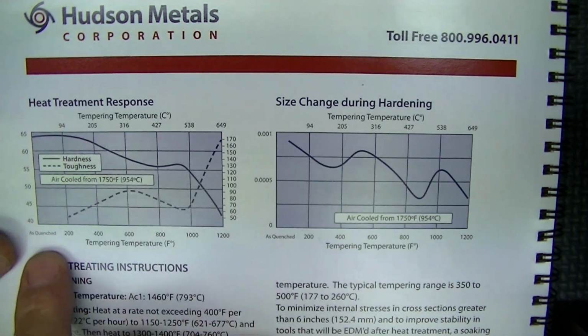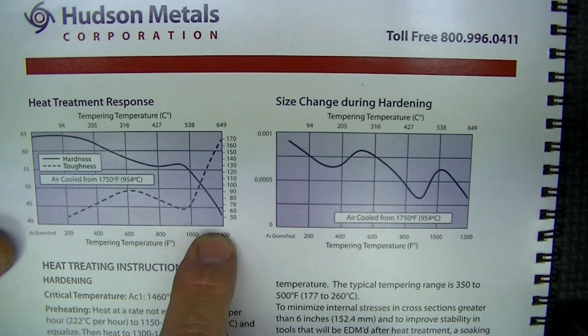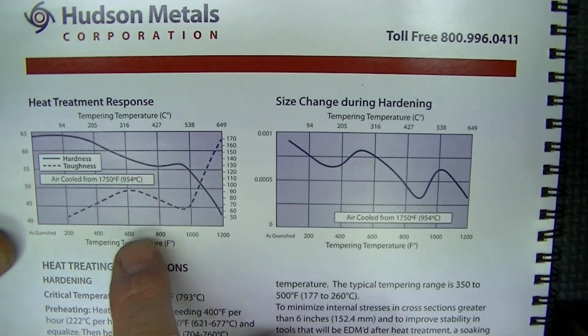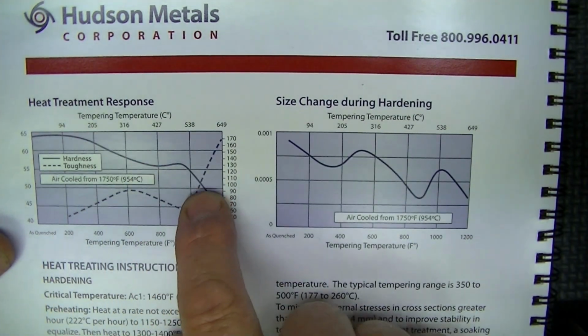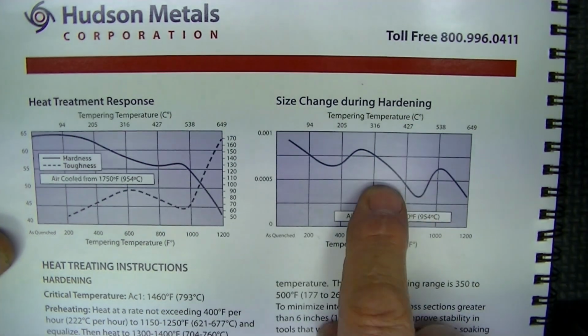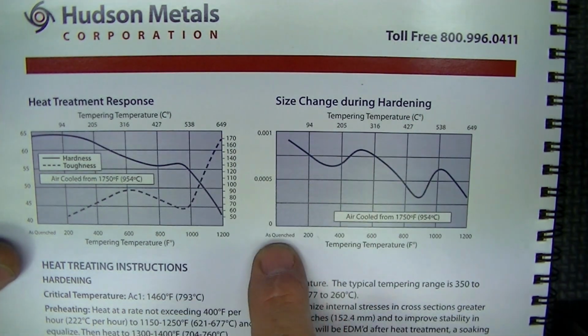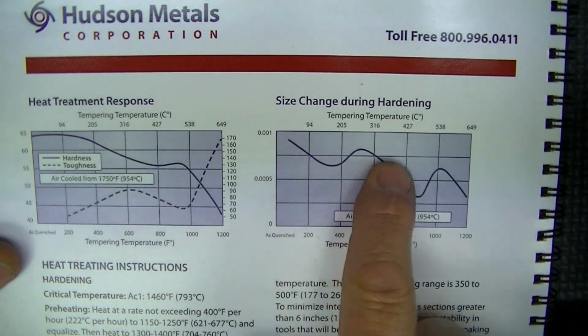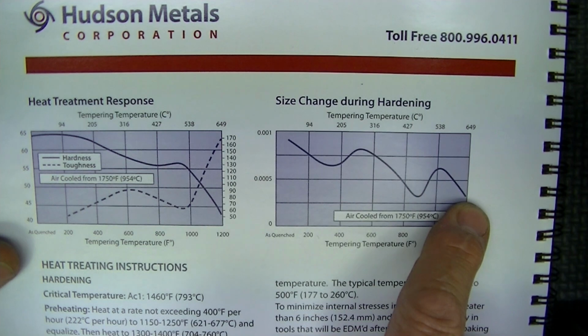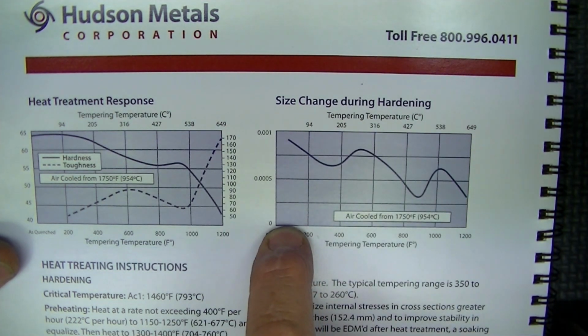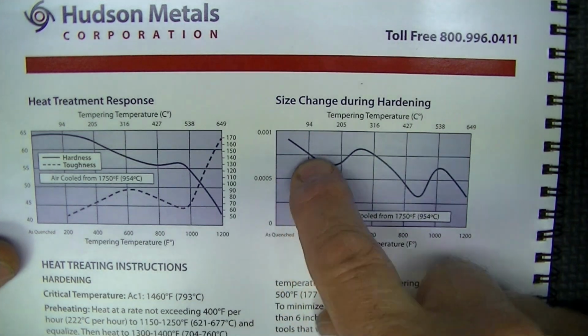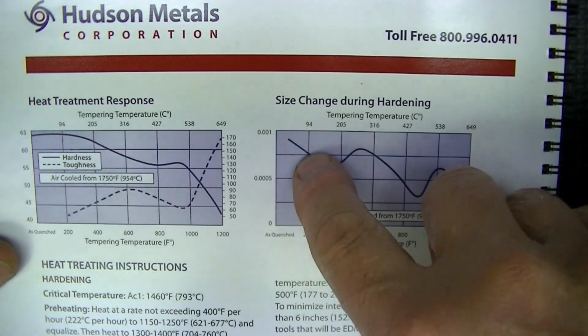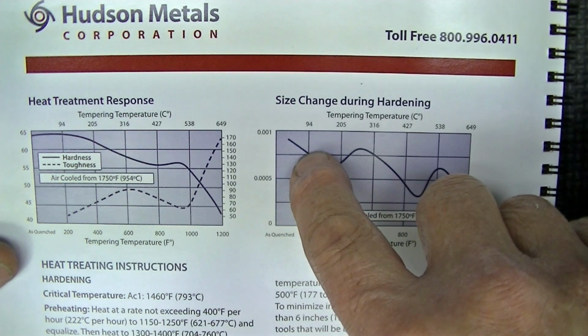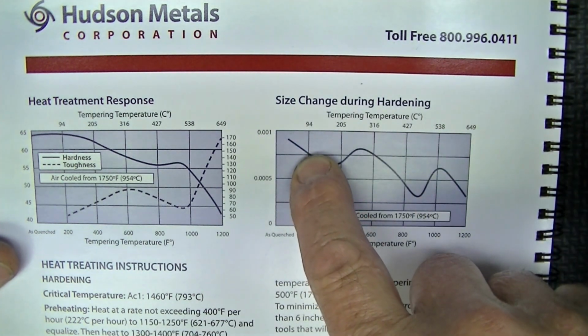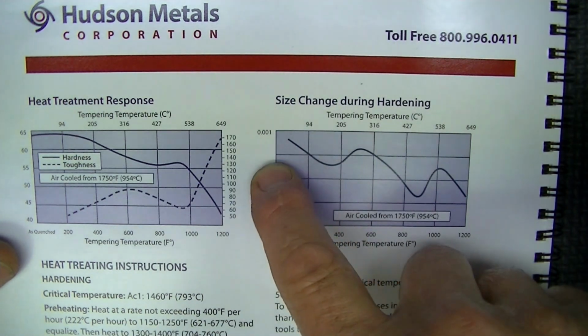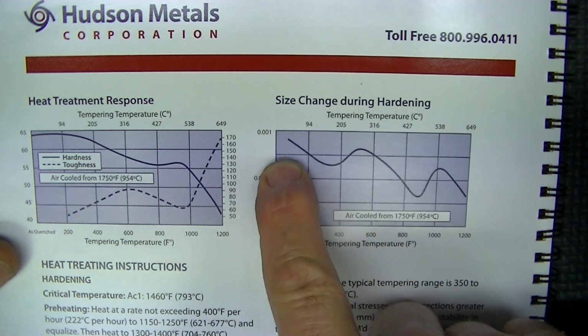And this chart shows hardness relative to temperature. Rising temperature obviously comes down and gets softer, and then toughness is shown here also, and obviously at higher temperature the toughness gets higher. On this side we're looking at size change during hardening, and these are all tempering temperatures, and you can see there's quite a variation of where the material goes to relative to its initial unhardened condition to the hardened condition. And here we're seeing it at roughly 200 degrees Fahrenheit, which would be the highest hardness that this would be done at. We would probably get 7.5 ten-thousandths of an inch per inch of growth.